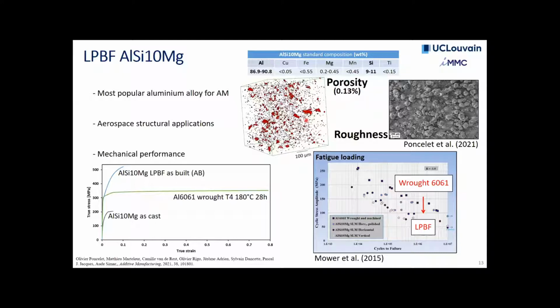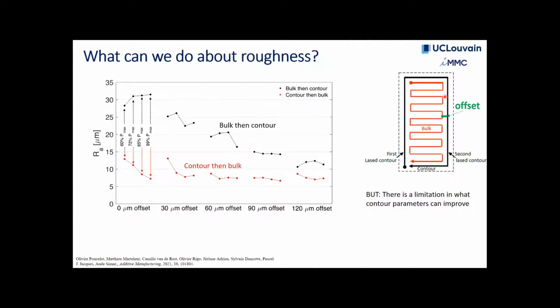The impression is, of course, that you have a lot of porosities, but that's the 3D effect. And also you have a lot of roughness on the surface. So one of the questions we ask is, can we do something about this level of roughness? And so that's something that Olivier Poncelet and Camille and the rest that are with us today are having a good look at. They built some walls and looked at bulk and the contour, because we know that maybe one solution would be to improve the contour of these materials, or adapt the contour